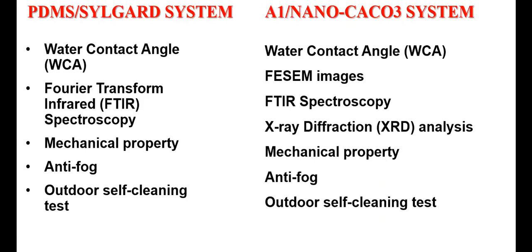Next, once we get the best blending ratio of PDMS and Sylgard, we introduce nano calcium carbonate into that system and we do the same characterization. But now we also use FESEM to see the dispersion of the nano calcium carbonate on the substrate, FTIR spectroscopy to see the cross-linking ability, and water contact angle to see whether it is becoming more hydrophobic or less hydrophobic. Apart from that, we do X-ray diffraction analysis to see how the calcium carbonate is bonded, whether it is on the surface or inside the coating system. And then we look at the mechanical properties, the anti-fogging properties, and outdoor self-cleaning testing as well. So these are the tests which we carried out.